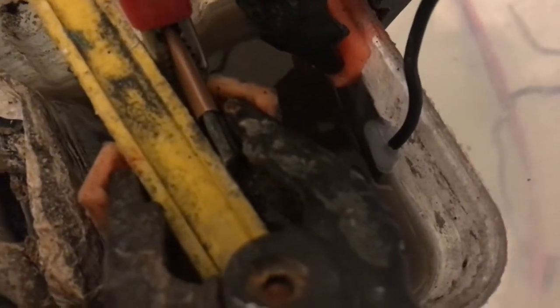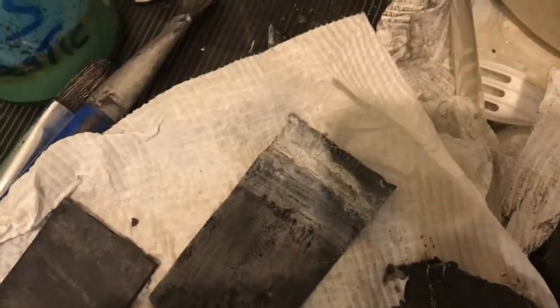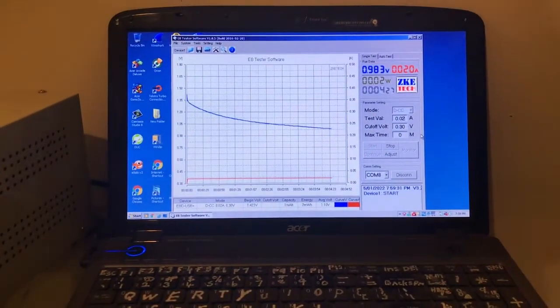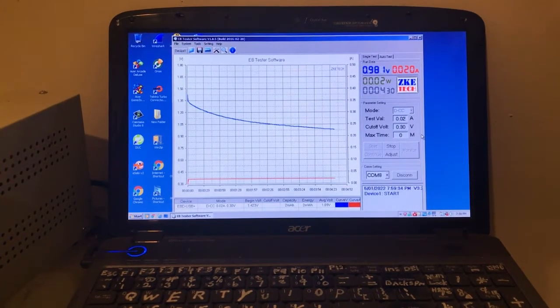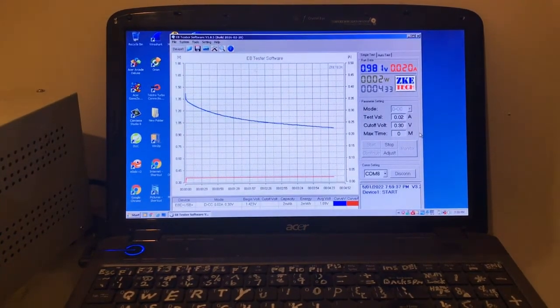I put another piece of zinc in there where I could solder on a piece of wire and put some glue around it. It's the same size as the other piece, just this one's a brand new piece, so it's not damaged. So I'll do a couple of charges with that, and then I might set up the new cell with higher cement content and give that a run. I'll get back and see how long this actually runs for, about just after its hour. So it ran for an hour there, and this is the remainder with a zinc plate.